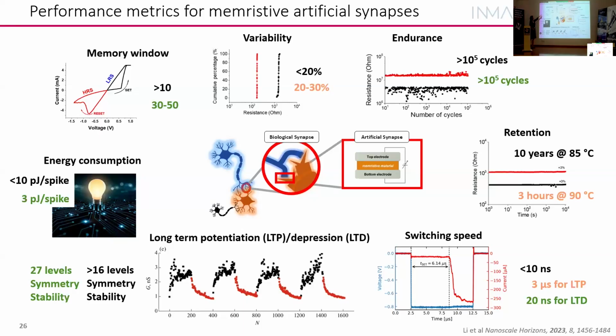So we've achieved a very good window, very good endurance. We have very fast switching speed for the depression, but not for the potentiation. We have lots of levels. We have a very low energy consumption. So there's only the retention that we still have to improve, and the variability, which still can be improved.